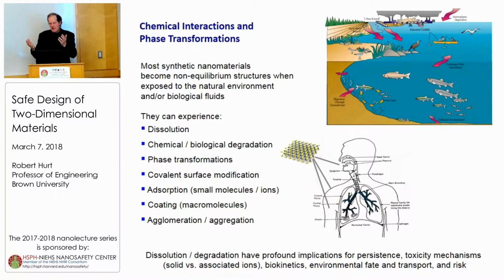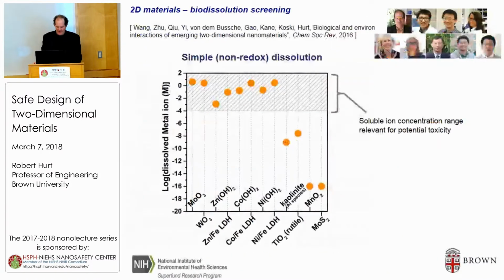In dissolution scenarios, one is exposed both to the particle and to the soluble ions. And a classic example is silver. And about a decade's worth of work on silver over the last period has shown that most of the biological effects associated with silver nanoparticles are really due to the ion. And you cannot understand the data or behavior on silver unless you understand that the particle is really an inventory, a high-density collection of atoms waiting to be oxidized and dissolved to produce the bioavailable and bioactive silver ion, which is the actual toxicant.